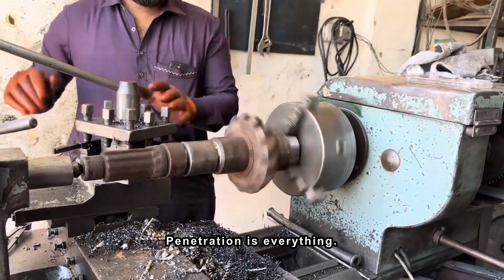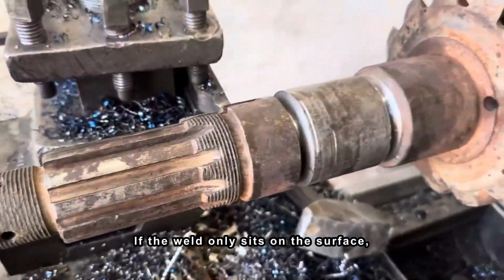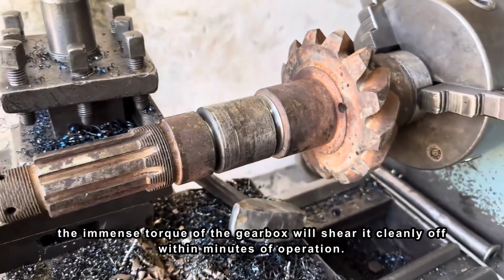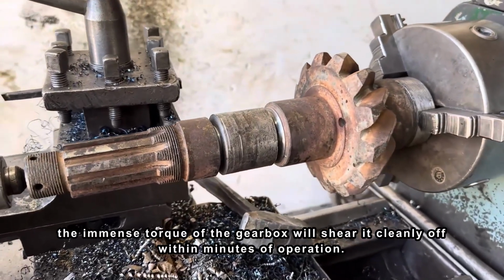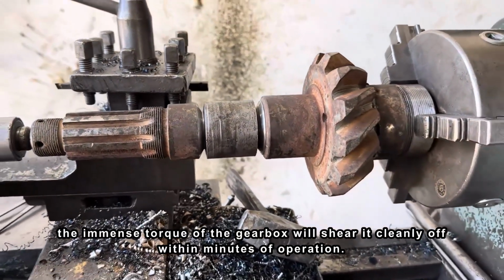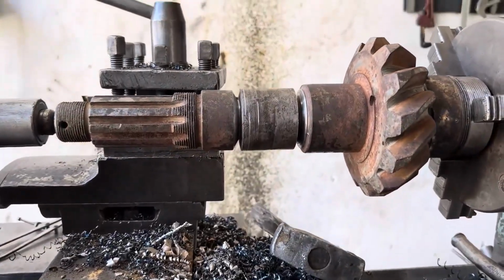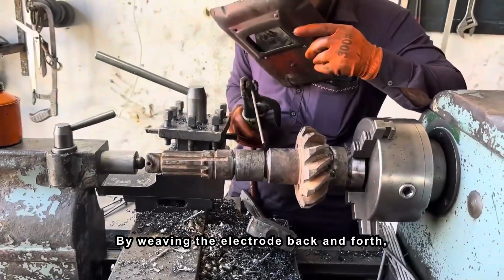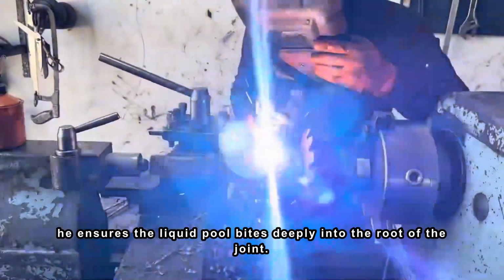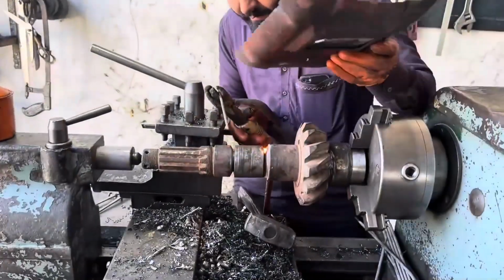Penetration is everything. If the weld only sits on the surface, the immense torque of the gearbox will shear it cleanly off within minutes of operation. By weaving the electrode back and forth, he ensures the liquid pool bites deeply into the root of the joint.